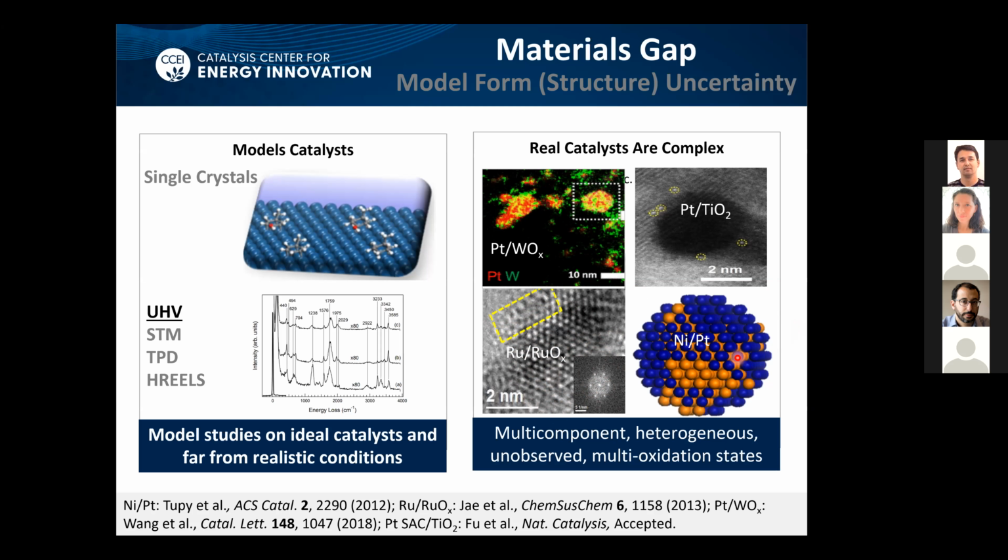This is a nickel platinum bimetallic catalyst. We take spectroscopic data, XAS, and we try to fit atomistically through some reverse Monte Carlo, for example, and try to figure out where is the nickel, where is the platinum. In the case of biomass, the nickel is more oxophilic. It's been pulled to the surface, and so you see that blue on the surface, but it's not a perfect monolayer of one thing on another. We see a lot of platinum-exposed defects, and so the structure of this catalyst is quite complex.